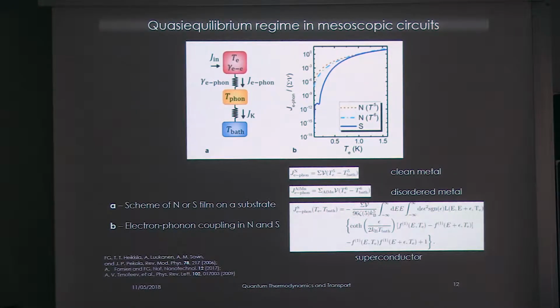As I was saying, the important thing is to define a temperature. We are in a quasi-equilibrium regime. What is the scheme? This is a very simplified cartoon of a normal or superconducting film deposited on top of a substrate. We inject some heat current inside, heating the system. The electronic temperature can be defined thanks to large electron-electron interaction. And then there are, for instance, losses.